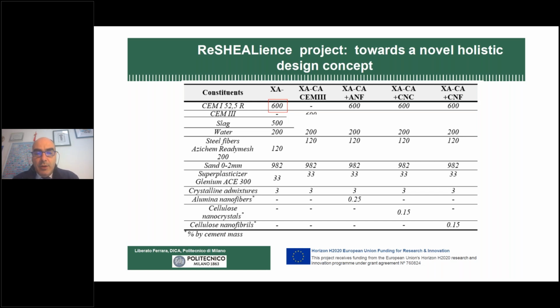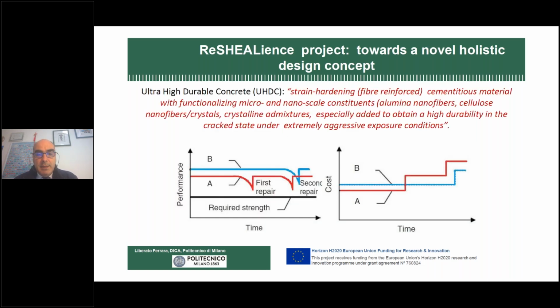Actually, if you consider an ordinary concrete with 350, 400 kilos per cubic meter of cement, to realize 1 meter of the wall of the basin, which is 10 centimeter thick, you need 40 kilos of cement. But in our case, with this mixed design, to realize 1 meter of the basin wall, which is just 3 centimeter thick, you need 18 kilos of cement. So in the end, you have a more than 50% saving on the use of the material. So think of the structural unit, think of the functional unit, and not of the cubic meter of cement.